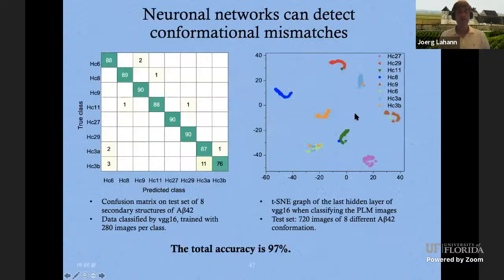Okay. So now the question is, how well can we predict the helical content of that peptide? And so we created 8 different variants again. We compared them with each other. And while there are potentially a few more mismatches here, overall, they still cluster very nicely. And the accuracy in this is again very, very high. So this is really exciting because now you can not only predict a structural difference, but you can also predict misfolding within those peptides.